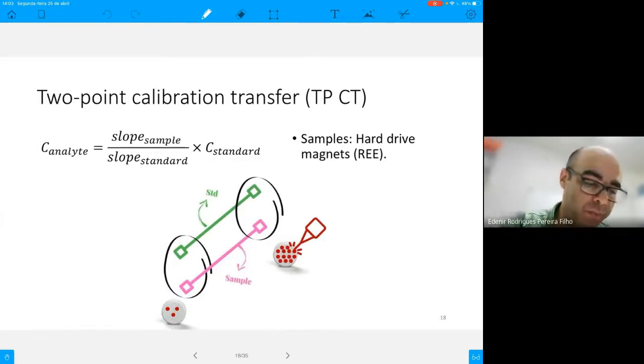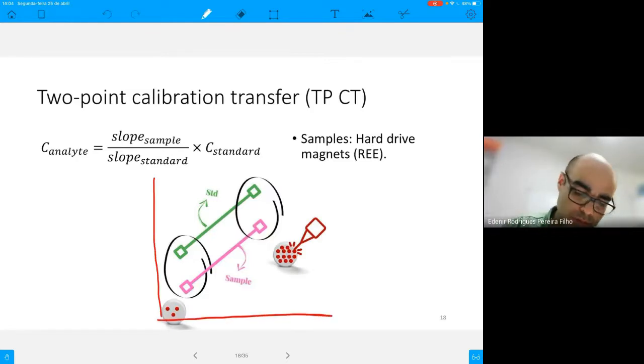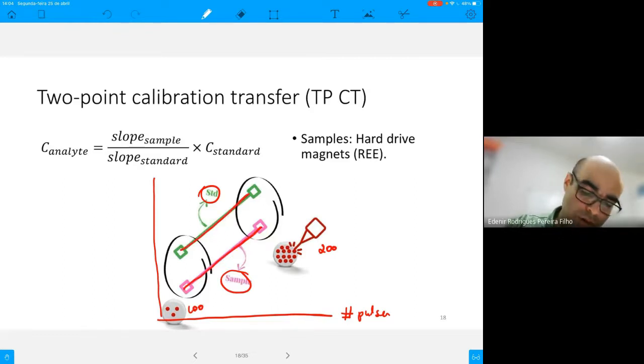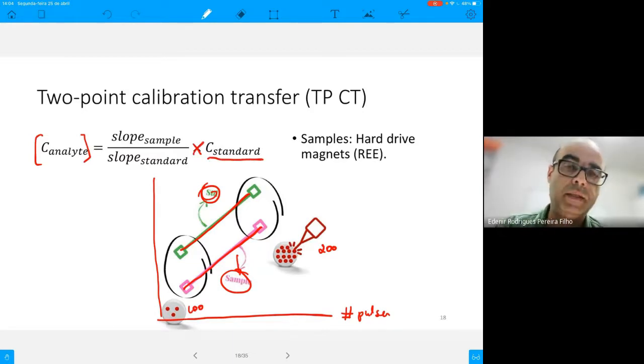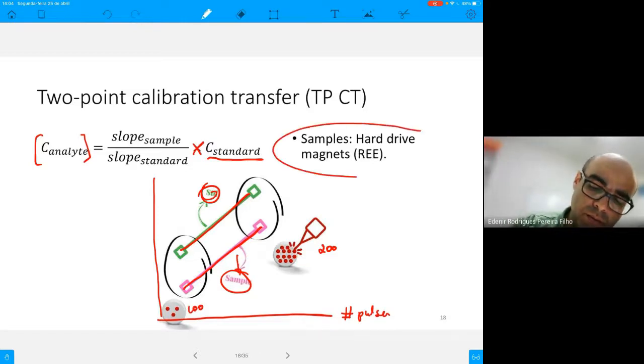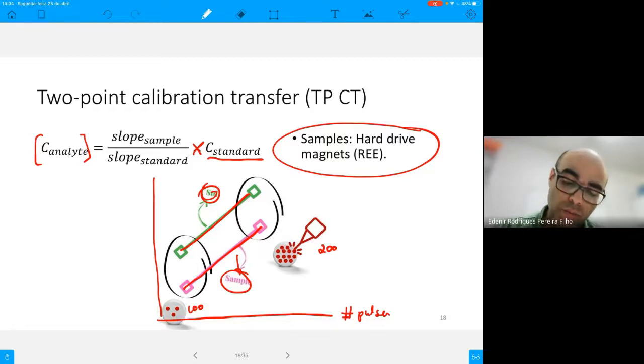The other strategy is two-point calibration transfer. In two-point calibration transfer, we prepare pellets of the sample and also of the standard. The standard can be reference samples. And we perform several numbers of pulses. For example, 100 pulses here, 200 pulses here, and we can calculate a linear model for sample and for standard. And the analyte concentration will be the slope of the sample divided by the slope of the standard times concentration of the analyte in the standard. We use this strategy in order to calibrate hard drive magnets. We are interested in determination of rare earth elements.